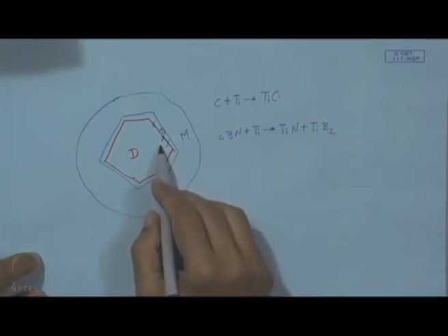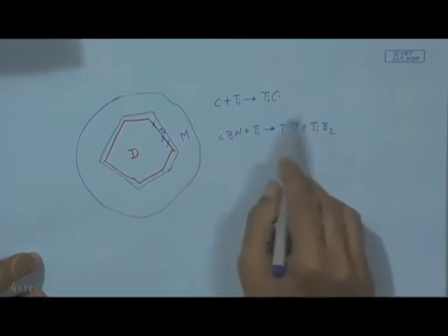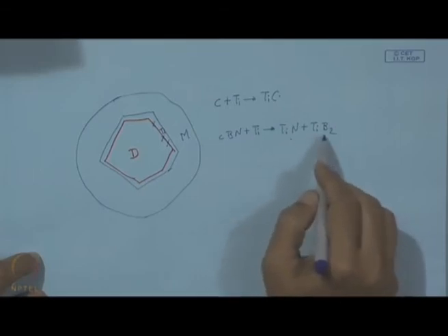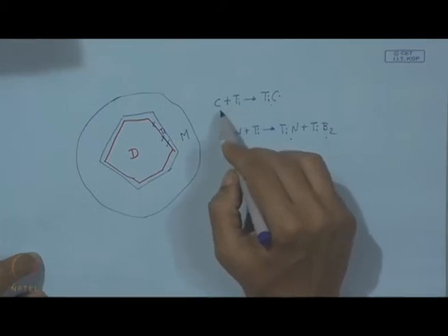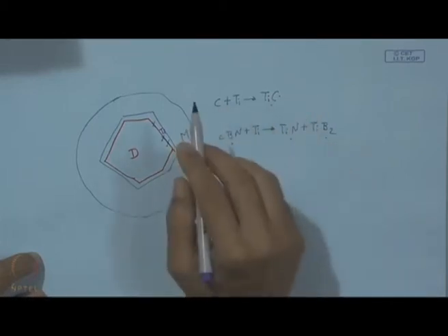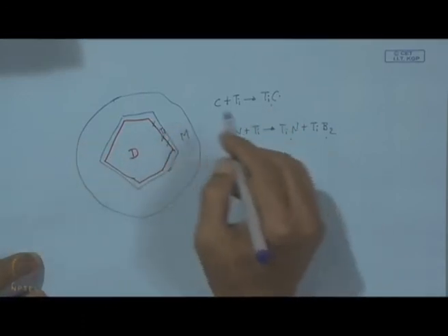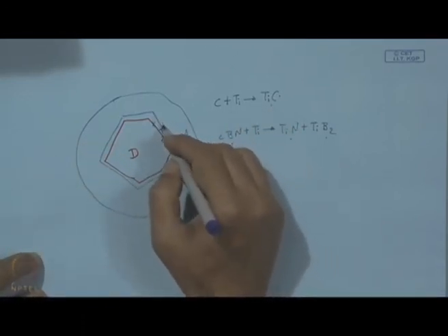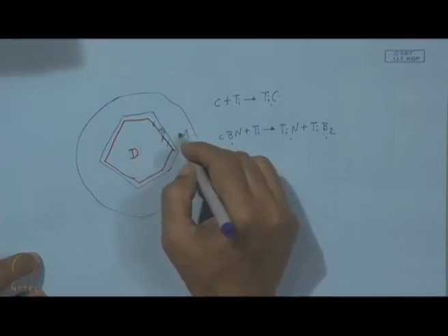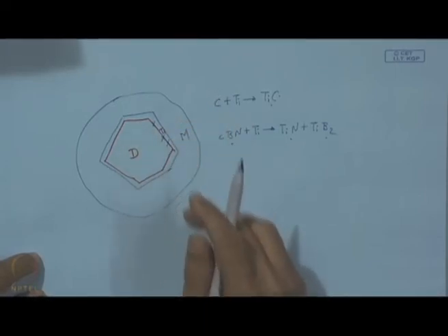So, this chemical attachment, chemical bridge formation, is quite possible because of this thermodynamic property. These are more stable than this one, this TiC is also more stable than carbon. So, this part is well accepted, but what we can see further to this, the outer surface of titanium can have good bonding with this conventional metal matrix and we get a very good bond.